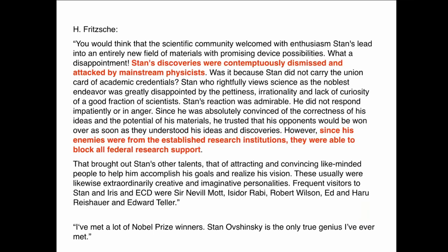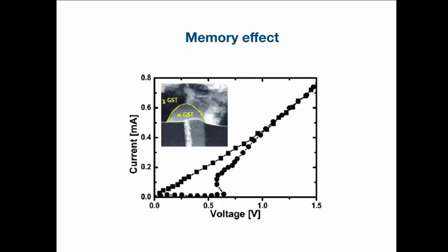Ovshinsky's paper in Physical Review Letters received two strongly negative reviews, but the editor decided to publish it anyway. The switching effect he discovered was one phenomenon, but some compositions showed a memory effect: when an electrical field is applied, the film switches from a high resistance state to a low resistance state, and stays there when the field is removed.